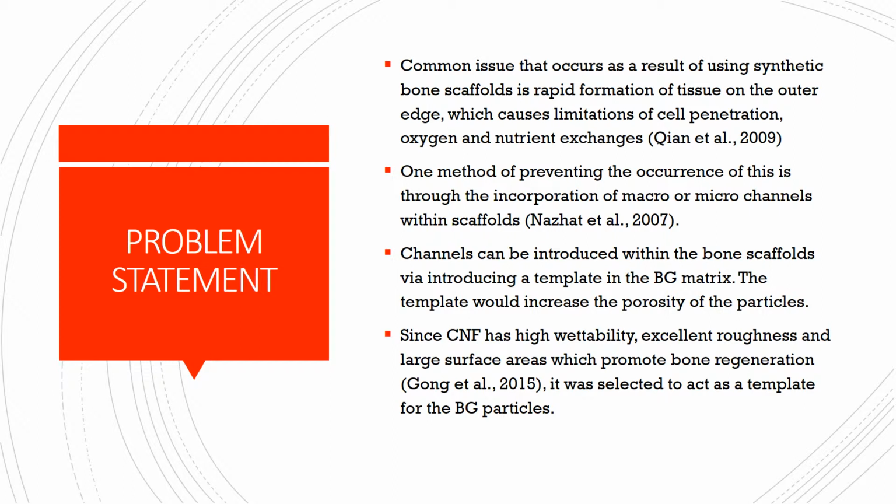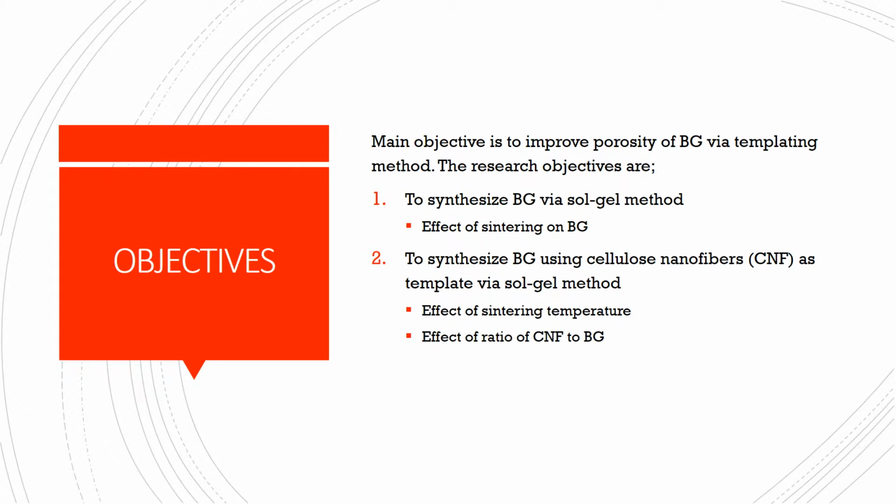Problem statement. A common issue that occurs due to the bone scaffolds is limitation of cell penetration, oxygen and nutrient exchange. One method to prevent the occurrence of this is by incorporation of macro or micro channels within the scaffolds. Since CNF has the highest wettability, roughness and large surface area, it is selected to be a template for the bioactive glass particles. Main objective of this research is to improve the porosity of bioactive glass via templating method.